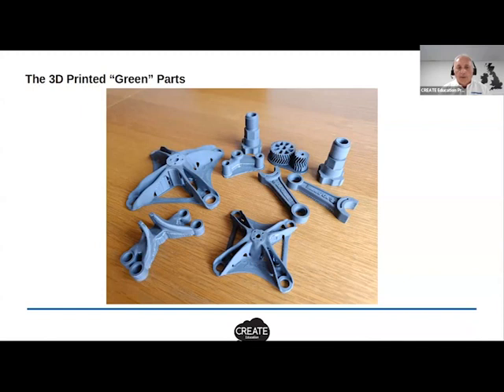It's called Ultrafuse, and it's available in two stainless steel varieties, 316L and a 17-4 PH version of stainless steel. The makeup of that filament is just under 90% stainless steel powder, held together by a polymer binder. The polymer in this material is called POM, and that plastic polymer is effectively holding the stainless steel powder in a matrix, in filament form, which allows you to 3D print with it, just like you would any other filament for polymer printing.